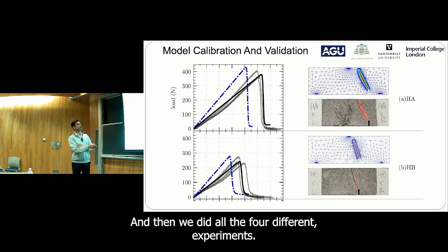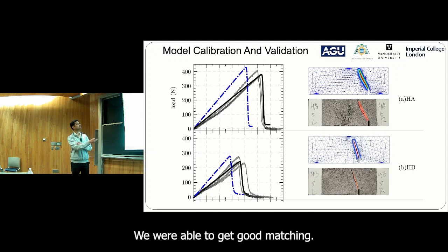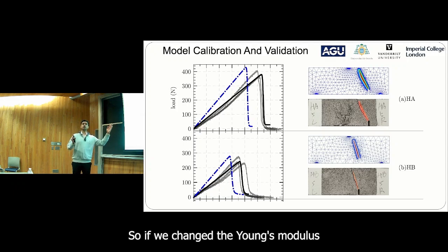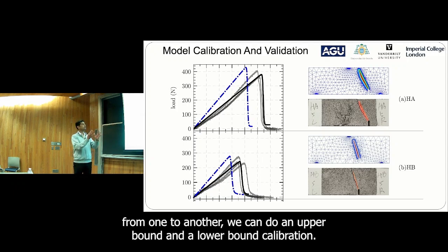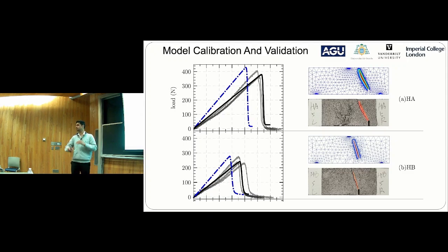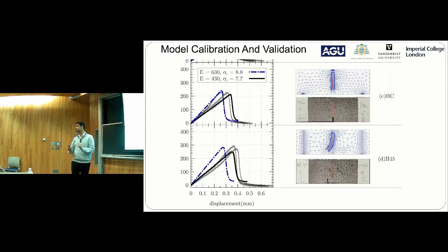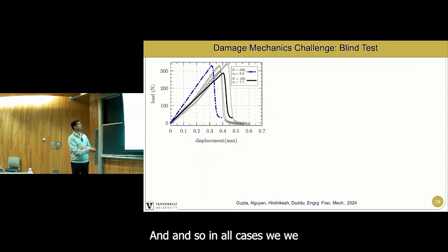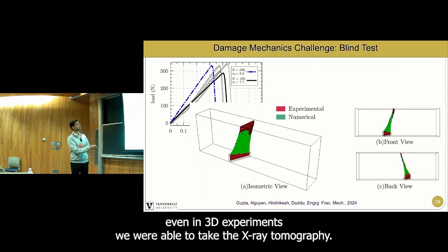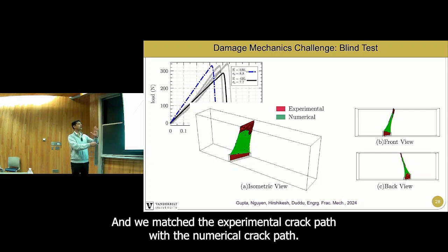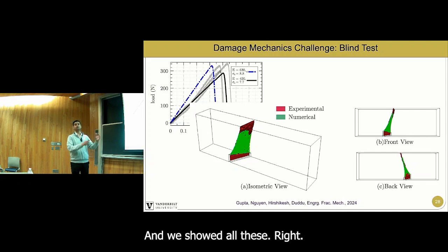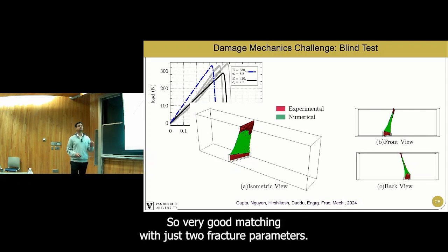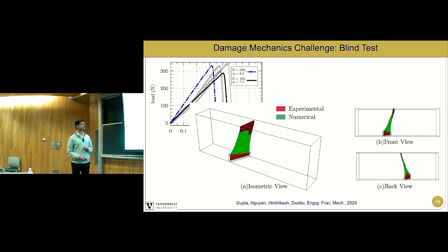And then we did all the 4 different experiments. We were able to get good matching. The blue and the black are bounds. So if we changed the Young's modulus from one to another, we can do an upper bound and a lower bound calibration because experiments always have variability, correct? And so in all cases, even in 3D experiments, we were able to take the X-ray tomography and we matched the experimental crack path with the numerical crack path. And we showed all views, right? So very good matching with just 2 fracture parameters.